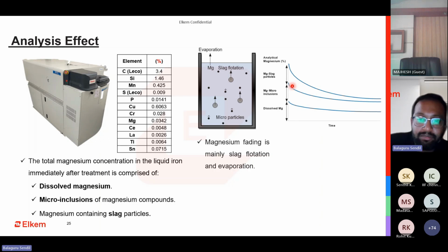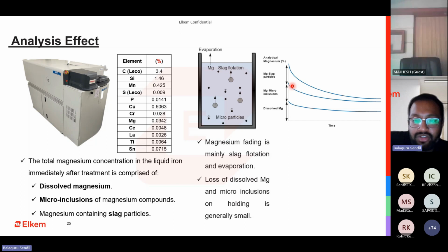So magnesium fading is mainly slag floating and evaporating out. The loss of dissolved Mg and microinclusions is generally very small. The dissolved Mg doesn't get lost. It's very difficult to lose that. Unfortunately, if you're holding for some breakdown, maybe it loses. So this is the hierarchy in which the magnesium loss happens. What you are measuring here is a combination of dissolved magnesium, magnesium that is evaporating out, simply going out as waste, and the slag flotation.